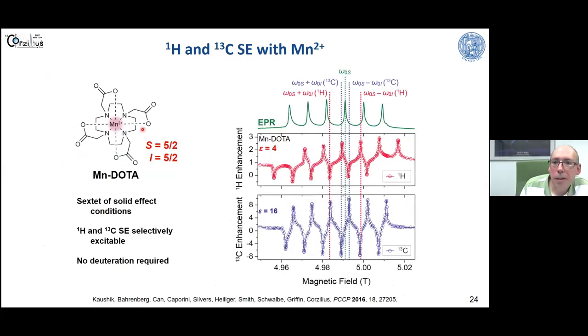You can use manganese. With manganese, you get a splitting practically of your EPR resonance of your central transition into six lines due to the hyperfine coupling of the manganese 55 nucleus, which is a 5/2 nuclear spin. But fortunately, this is also mostly isotropic due to the S character of the electron spin. But you have to live with these six intercalated field profiles practically of DNP, which reduces the final efficiency.